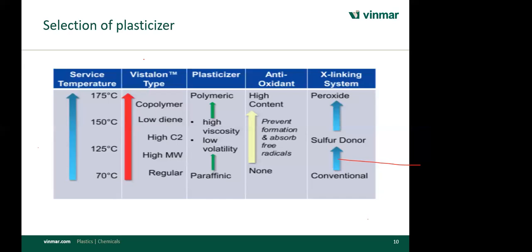And in peroxide, please remember, don't use HVA-2, since in most cases I found people are mixing up. Once you buy peroxide, they buy coagent, even though in some cases the coagent price is higher. But don't use HVA-2 with peroxide system, since exclusion of oxygen from the system is practically impossible, except in a salt bath curing system.